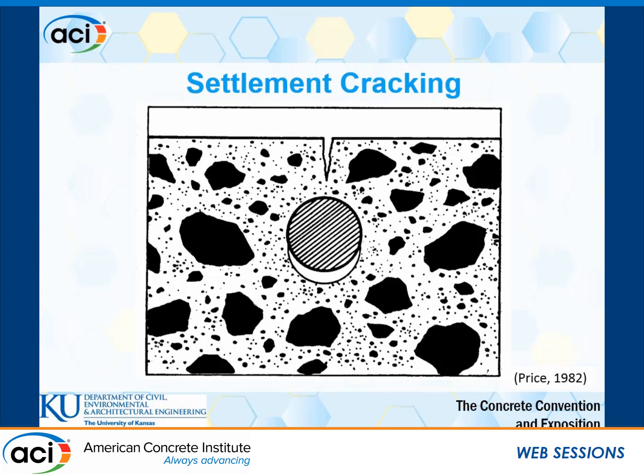That's why you see settlement cracks within one or two days after construction. In most cases, the built-up tensile stress is not enough to crack concrete. However, the stress will create a plane of weakness. And later on, when shrinkage kicks in, when you start to load your bridge, or when you have thermal exchange, the stress builds up and the crack will open. Settlement cracking can be a major durability problem because the cracks occur directly above the rebar and run parallel to them, potentially exposing the full length of the bar to de-icing chemicals, oxygen, and moisture, causing corrosion.